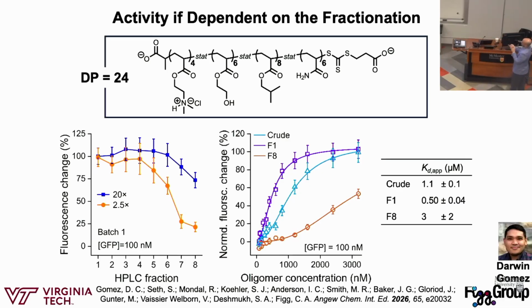Then as we go on, we see the hydrophobic ones don't bind as much at these low concentrations of oligomer, but if we add 20x in, it's a little higher. We can also show that from the crude polymerization, we can split the apparent dissociation constants into stronger binders and weaker binders. You'll notice these values are a little different. I just want to talk about that for a minute.